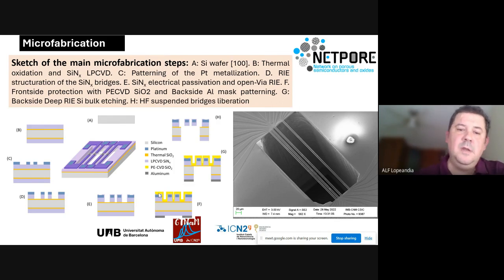in the final steps. In the backside here, as you have seen, we put an aluminum mask in order to be able to do DRIE in the G step. And we stop without breaking the membrane. We stop in the silicon dioxide, and we finally liberate everything with HF immersion and supercritical drying, in order to liberate that structure that you can see here, which are beams of around 1.5 microns width, with a thickness of 450 nanometers, and that are 400 microns length.